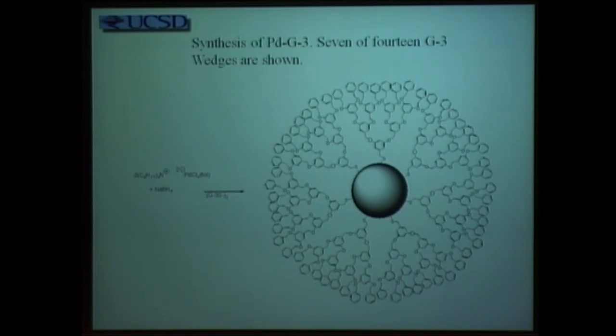This is of great importance to a lot of people interested in catalysis, because without this covering, the palladium in these reactions precipitates very rapidly. But it's 10 times more reactive, despite the fact that surface approach onto the catalytic surface takes place at a different rate. So I hope what I've been able to show you today is that by logically thinking about structure,